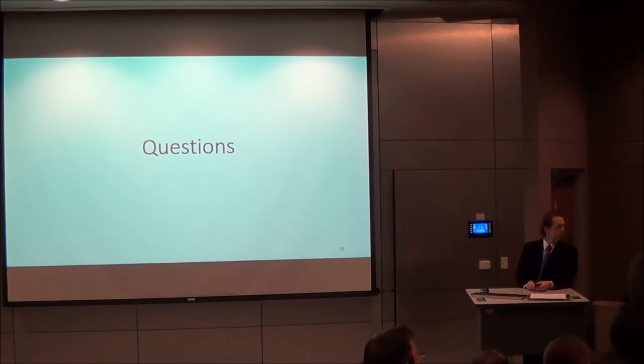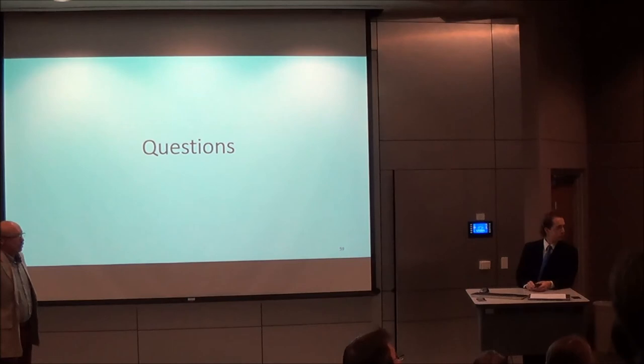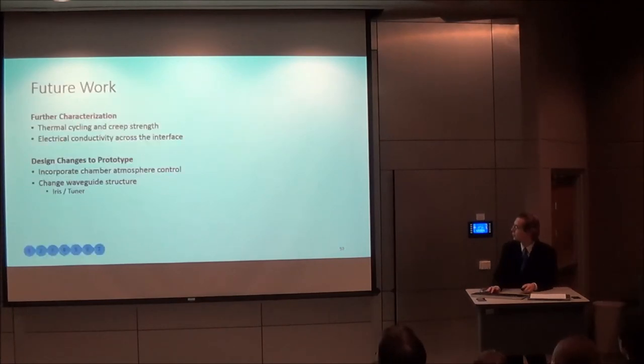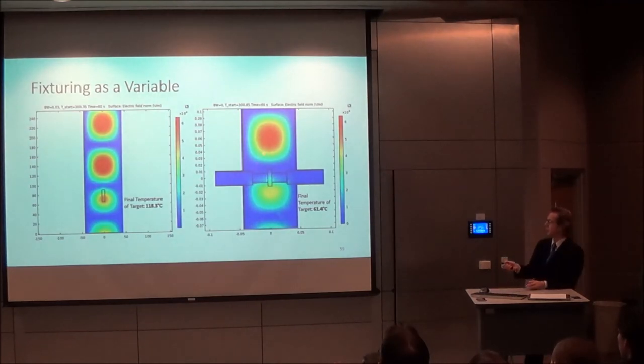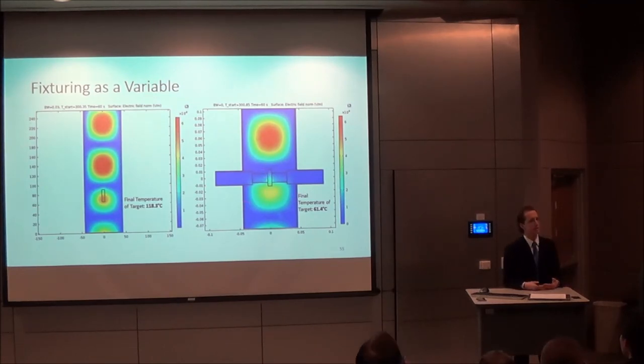Is there any experimentation with moving that peak around on either of the two things being joined together? Would it make more sense to move that peak around on one side or the other? For instance, moving it from one side to the other, is that what you mean? So this is just one back wall position, but by varying the back wall position, I am able to move the peak. But there's a limit to what can actually be achieved, because basically you'll see this hot spot move down and then reduce intensity, and then hop over here and then increase intensity. So there's just a fundamental problem with actually coupling to the target that has to be overcome by using other methods. The back wall gives very limited range of control, and that was one of the few things we could change with the closed loop control system. So that's why I removed it.